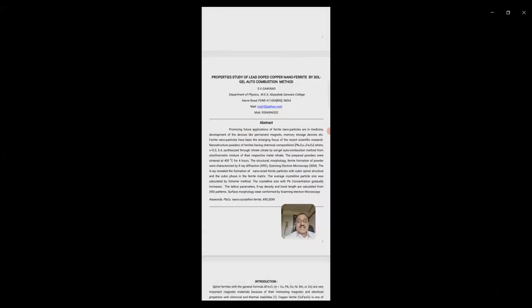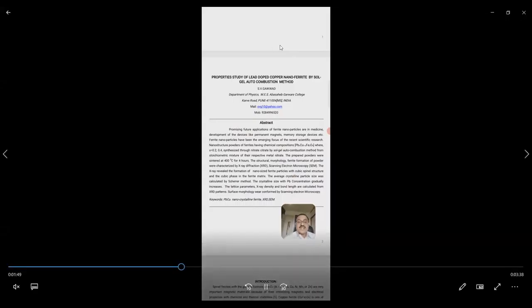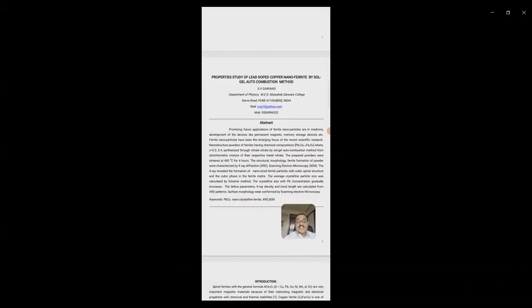The structure, morphology, and ferrite formation of the powder were characterized by X-ray diffraction and scanning electron microscope. The X-ray revealed the formation of nano-sized ferrite particles with cubic spinel structure and cubic phase in the ferrite matrix. The average crystallite particle size was calculated by the Scherrer method. The crystallite size gradually increases with Pb concentration. The lattice parameter, X-ray density, and bond length are calculated from the X-ray pattern. Surface morphology was studied by scanning electron microscopy.